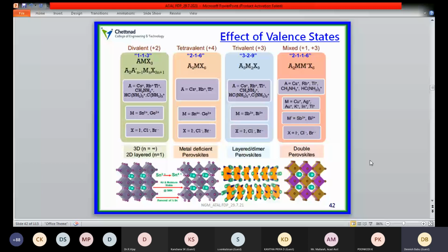Here I can mention different A site, M site, and X site cations. Here I have mentioned only the lead-free systems. Instead of lead, people can use tin, germanium, bismuth, antimony, and other materials. In some places people have started to use two M site cations, that is the 1 plus and the 3 plus cations. For the 1 plus cation, people use silver, gold, potassium, indium, and thallium based systems. For the second M site cation, people use antimony 3 plus and bismuth 3 plus for the preparation of mixed double perovskite structures.